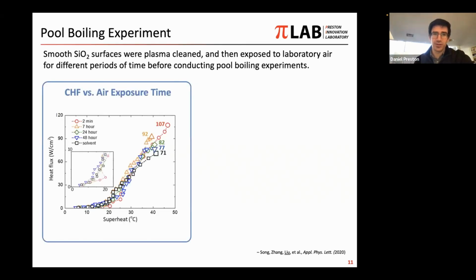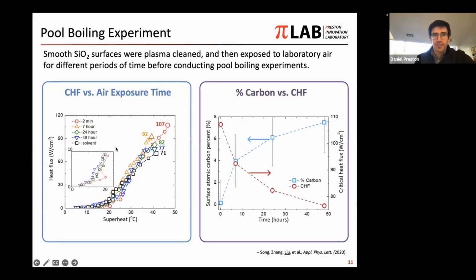Pool boiling experiments versus the air exposure time shown in the legend look something like this. And if we plot these on the same plot as the percent carbon that's measured on the surface, what we find is that there's sort of this inverse correlation. And so just leaving it sit out in the air in the lab over time, after a sample has been cleaned, will result in adsorption of carbon on the surface. It will become more hydrophobic, and that will really seriously impact your critical heat flux value. So this is something I've tried to make the point here that is very important to consider, even when you're doing fundamental studies, let alone trying to do things like enhance the performance with engineered wettability surfaces.